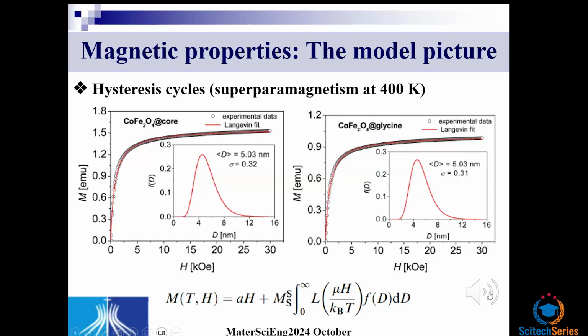So points here in the main plot are experimental data, and the solid red line going through the magnetization is the best fitting of the data using the model picture for superparamagnetism, which is represented by the equation in the lower part of my slide. The first term is just the diamagnetic component, and the second term is the contribution of superparamagnetism. So you can see here L is the Langevin function, and F is the particle size distribution described by the log normal. So from the fitting of both curves, you can extract the particle size distribution.